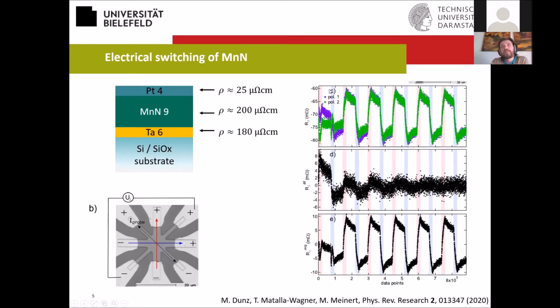We checked that this switching behavior is independent of polarity. So after a few cycles, we see that there is no more polarity dependence. So this is basically the signal. This average signal here is what we are going to look at.